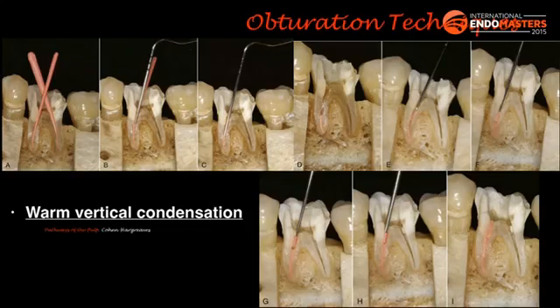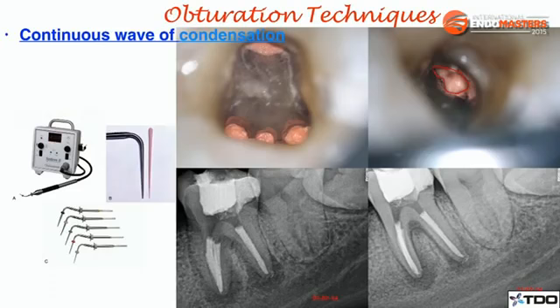The sectional method consists of placing 3 to 4 mm sections of gutta-percha, approximating the size of the canal, into the root, applying heat, and compacting the mass with a plugger. A variation of warm vertical compaction is the continuous wave of compaction technique. The increasing use of nickel-titanium rotary preparation techniques and the fabrication of standard cones of greater taper have resulted in more clinicians using thermoplasticizing techniques. The manufacturing of cones to mimic the taper preparation permits the application of greater hydraulic forces during the compaction when appropriately tapered pluggers are in use.